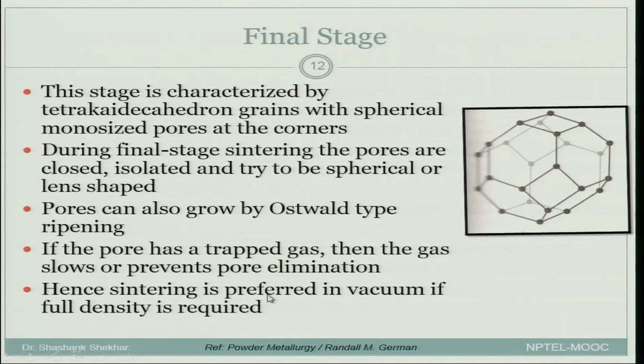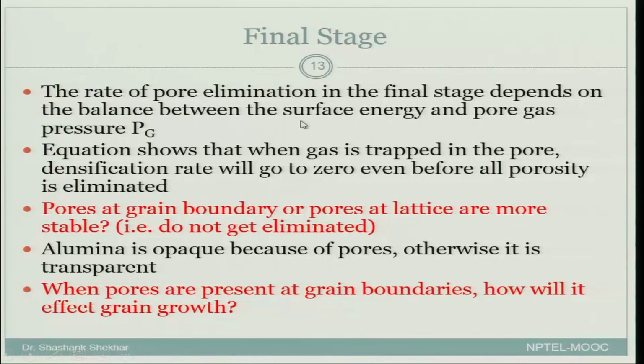The rate of pore elimination in the final stage depends on the balance between surface energy and pore gas pressure Pg. We will see the equation in a moment. So, this describes that the rate of pore elimination will depend on the balance between surface energy and pore gas pressure. The equation shows that when gas is trapped in the pore, the densification rate will go to 0 even before porosity is eliminated. We will see that in this particular case we will not be able to get rid of all the porosity. There is a possibility, not just a possibility, in most of the cases if you are doing it in some atmosphere, the pores will not be removed.